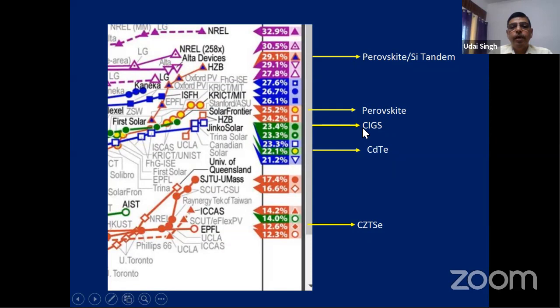CIGS, or copper indium gallium selenide, at lab scale the maximum efficiency achieved is around 23.4%. Cadmium telluride is around 22.1%. Copper zinc tin selenide, which has been in process, has a maximum efficiency reached of around 12.6%. So people are still working on that to get enhanced efficiency.